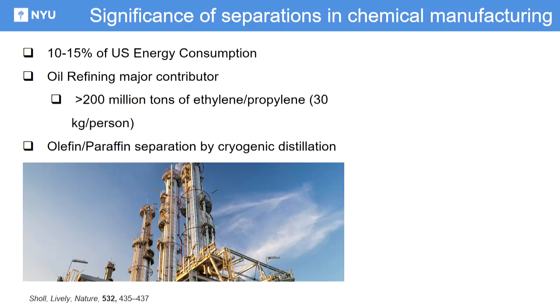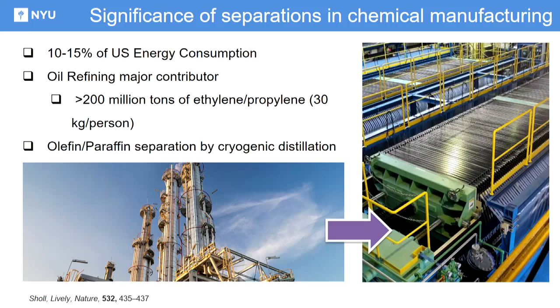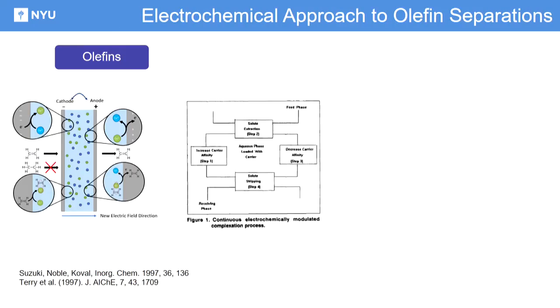Most of these processes are done through cryogenic distillations, which just the name sounds very difficult and energy intensive, right? And I think we can probably do better if we transform these distillation units into something that looks like a battery of electrochemical reactors. So this is not a new idea. Carl Koval and collaborators in Colorado in the early 90s started looking into electrochemical cycles to promote separation. So this is what I call an electrochemical swing absorber model, where you start with a molecule that has a high affinity, like copper-1, towards an olefin, and then you oxidize it to copper-2 when it releases the olefin. So you can send perhaps a feed into an absorption chamber where you have copper-1, and then you desorb it upon oxidation in a different chamber. And in this way, you can purify